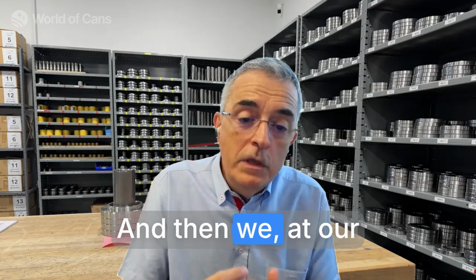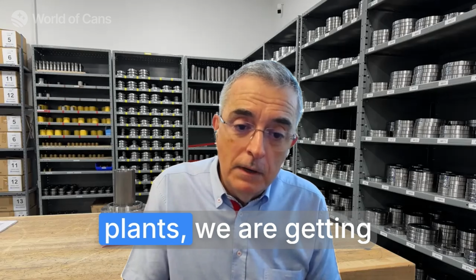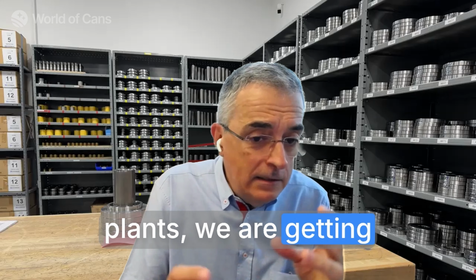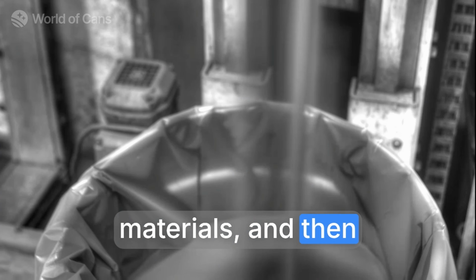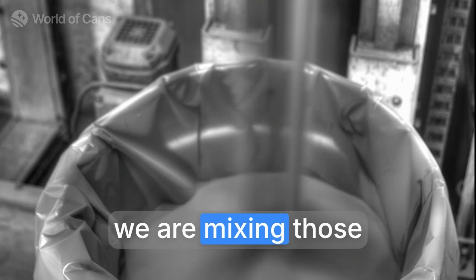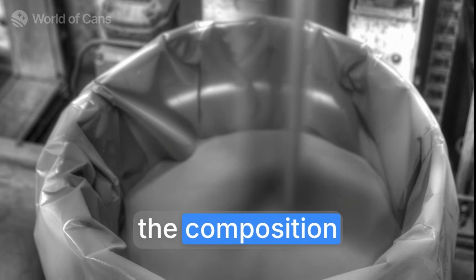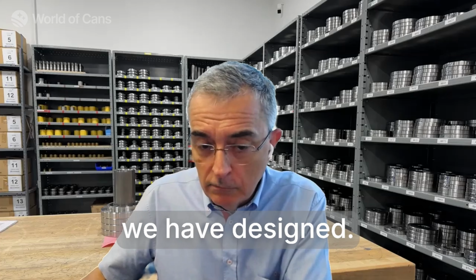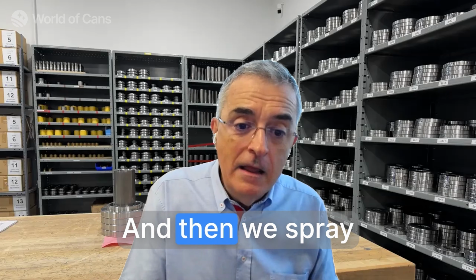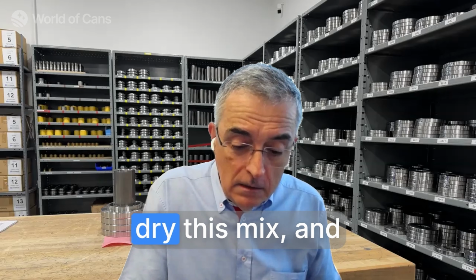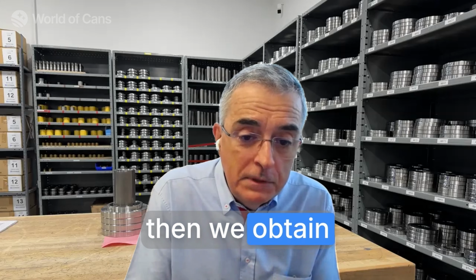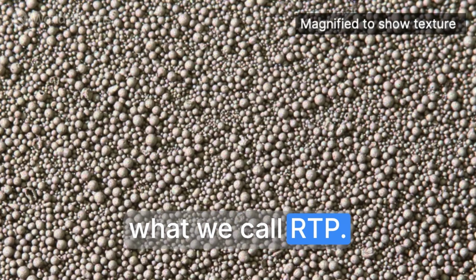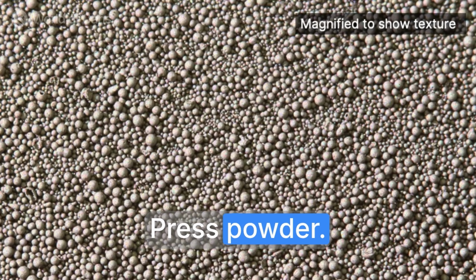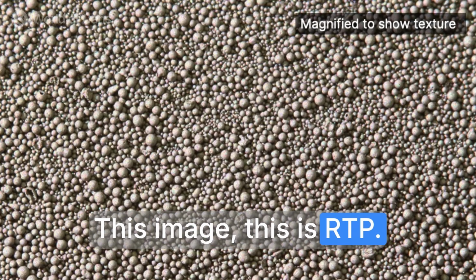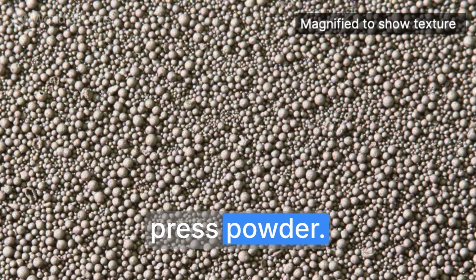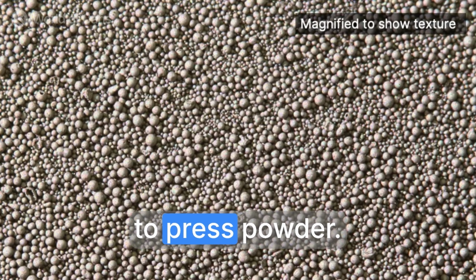And then at our powder manufacturing plants, we are getting the different raw materials, and then we are mixing those materials following the composition of the alloy that we have designed, and then we spray dry this mix, and then we obtain what we call RTP, ready to press powder. This image, this is RTP. This is ready to press powder, correct? Exactly. That's the ready to press powder.